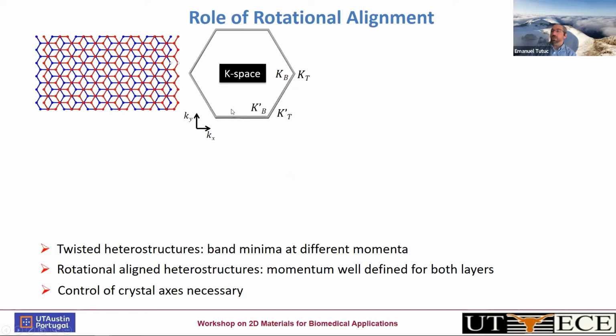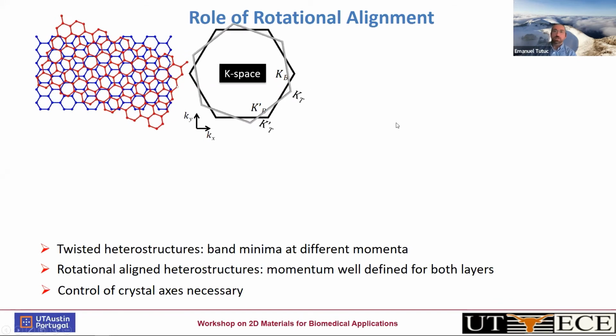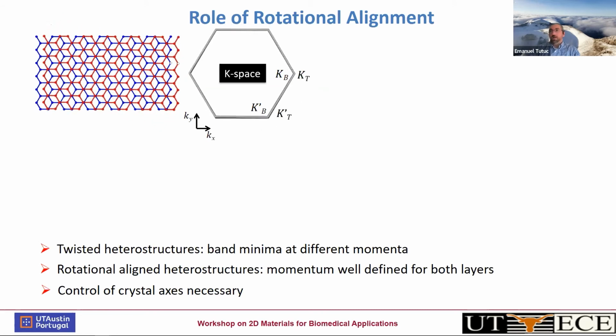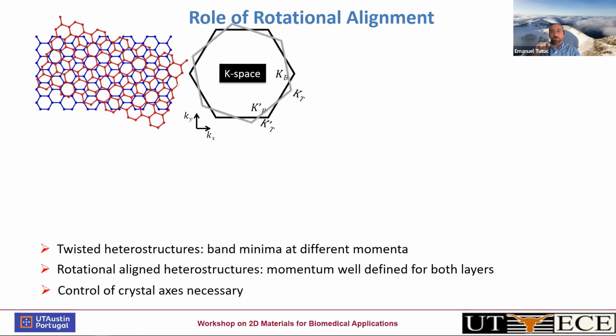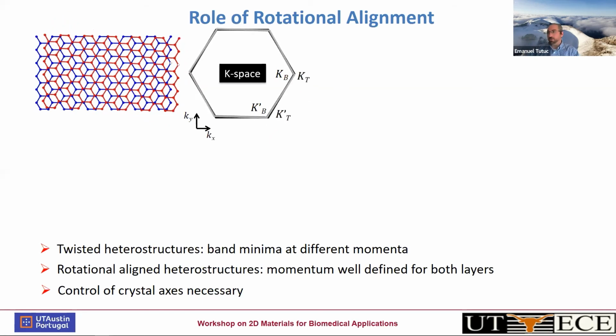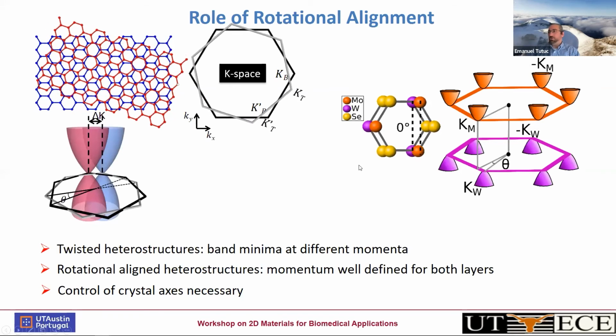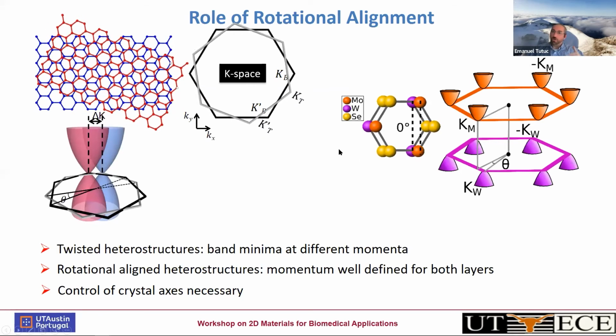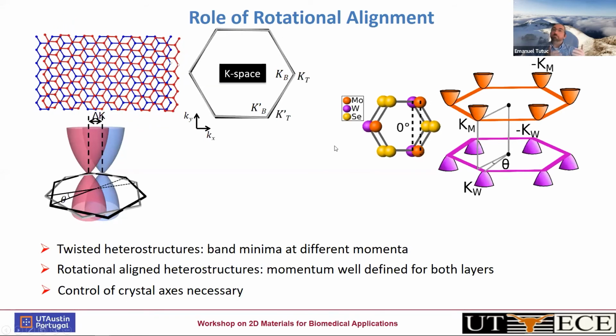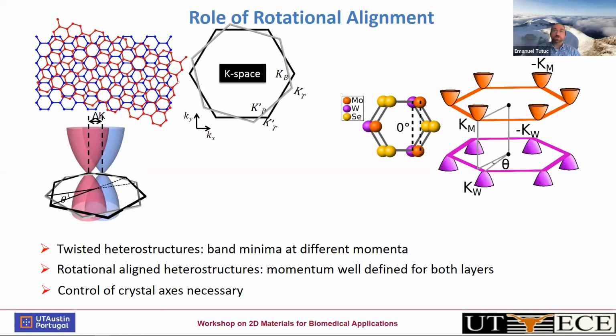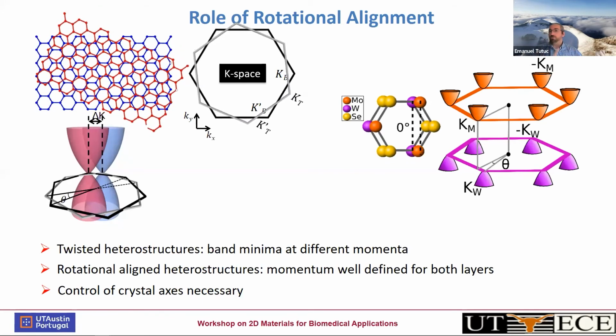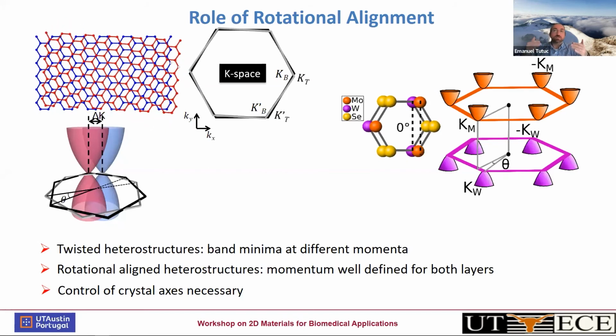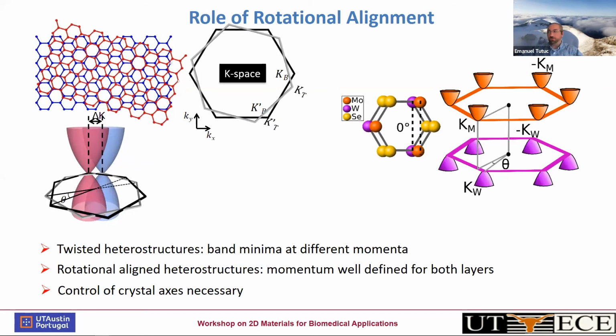One effect that we can also control is rotational alignment. And this is important in a heterostructure because direct alignment of the lattices also translates into a direct alignment of the Brillouin zone. And this is particularly important if we're interested in electrons moving from one layer to another, electron coupling from one layer to another. It's important for them to be at the same location in momentum space. That would ensure that, for instance, the electron momentum is a good quantum number across the heterostructure. In a covalently bonded heterostructure, this is generally a given because heterostructures grown by chemical vapor deposition or molecular beam epitaxy, thanks to the chemical bonding, will necessarily be registered from one plane to another.